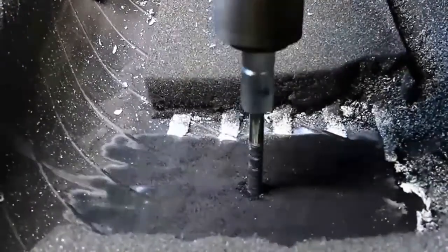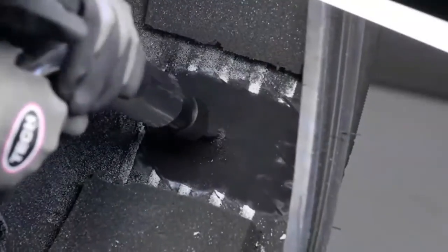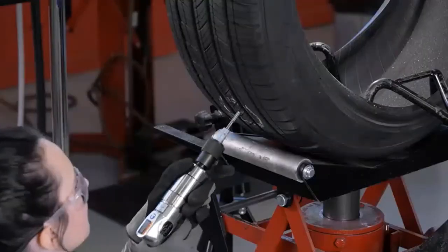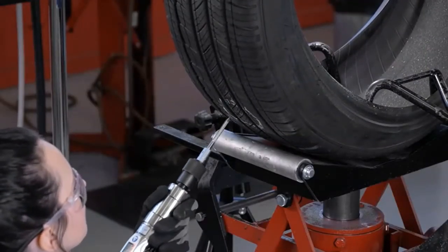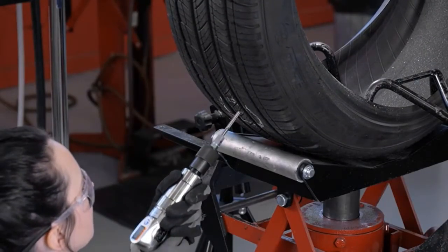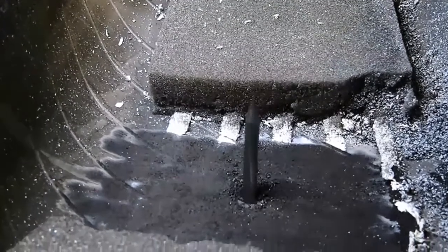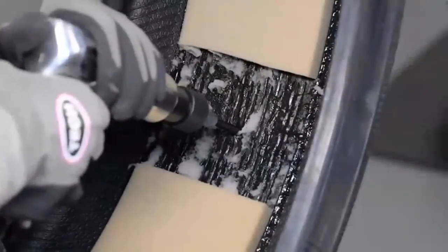When buffing the inner liner, be sure to run the buffing wheel from side to side across the inner liner as shown. This will prevent cutting grooves into the inner liner and promotes better adhesion of the repair to the tire. After you've achieved the proper buff texture, we'll use the appropriate size Tech carbide cutter in a low speed drill with maximum RPMs of 1200 to properly prepare the injury. This will also be the next step if the tire has a tacky adhesive.